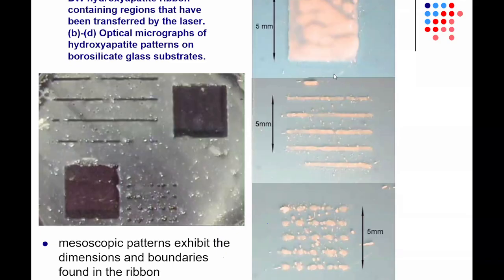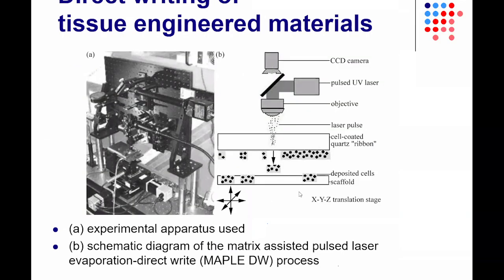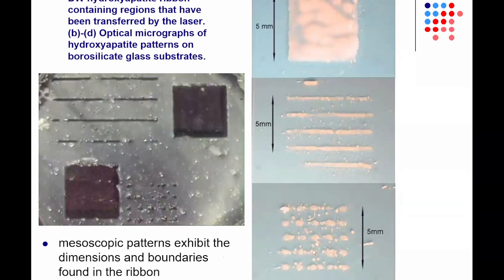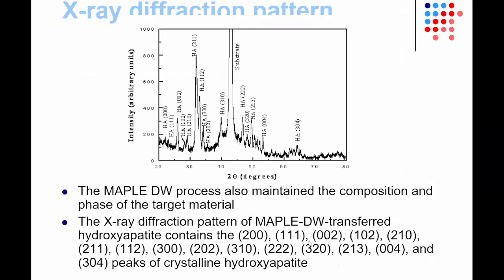You can see here the parts that are transferred. So this image on the left is the ribbon. This is the quartz. In this case, it's not coated with cells, it's coated with hydroxyapatite. And you can see here the regions where the excimer laser has moved the material onto the surface. Here you can see the processed structures. Here you can see the X-ray diffraction pattern showing that the processed material retains all of the crystalline structure of the input material. So you see here that it's a highly crystalline material that doesn't undergo any type of amorphization.